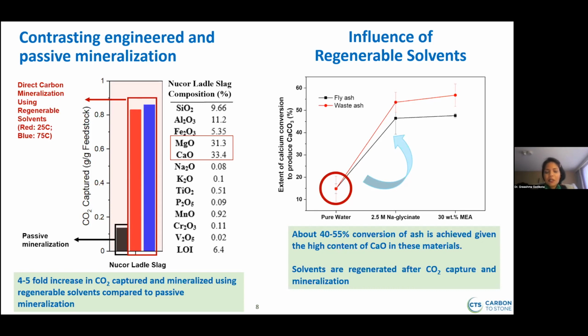So this is a very effective engineered strategy for fully utilizing the entire alkaline content as opposed to just partially using the alkaline content. Another key consideration is looking at different kinds of legacy waste. So for example, coal fly ash can be considered to be a legacy waste. If we simply react that in pure water, we just bubble CO2 through pure water, and we have a slurry of the fly ash with the water, we'll see that we get mineralization that's about 15% or so. But the moment we introduce sodium glycinate into the system, we get extensive mineralization that is 4 to 5-fold higher. So this is very attractive from the perspective of achieving higher efficiency in mineralization, because we eliminate the slow step, which is the CO2 dissolution in water.